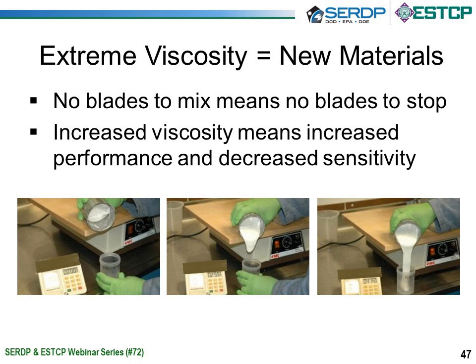The problem is as you decrease the particle size, you also increase the surface area, and you increase the viscosity of your material to the point where legacy technology won't mix the material. So again, with the RAM technology, because there's no blades to stop, you can get into viscosity regimes that are just completely inaccessible. The pictures on the bottom of the screen show a material that we mixed. At the time that we turned the vibrating table on, you can see the time that it takes to flow this material to the bottom of this container. So we're almost at 4.5 minutes.